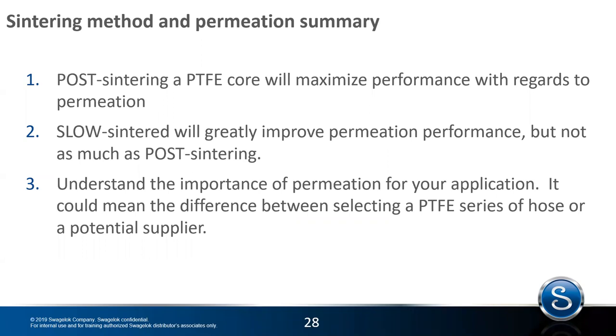So in summary, post-sintering a PTFE core tube is going to maximize performance with regards to permeation. Slow sintering will improve permeation performance, but it doesn't do as good a job as post-sintering. So it's important to understand whether you need permeation resistance in your hose, and if you do, come to us to help identify which of our products have the best permeation resistance. And we are currently working on this. As I said, we do have our lab set up now with the permeation test rig. We are testing our hose products so that we can compare one hose to another and identify the permeation rates of each.